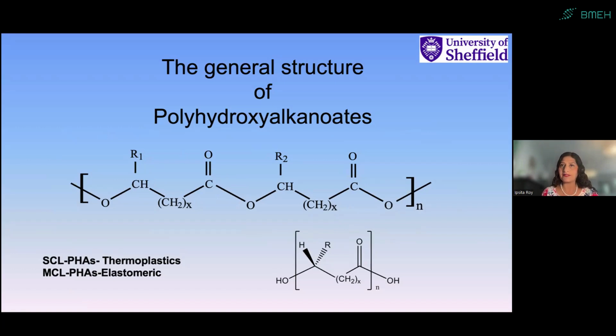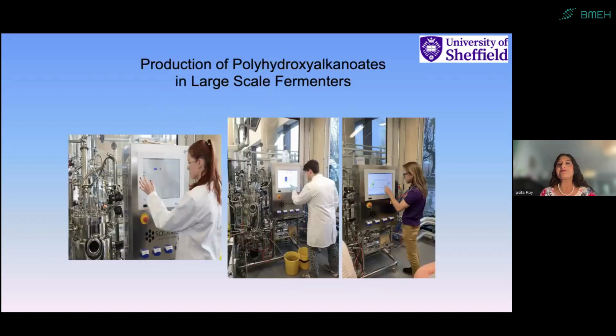The short chain length PHAs, as we call them, have monomer units going from C4 to C5, whereas the medium chain length PHAs are mainly monomer units going from C6 to C16. Normally the short chain ones are hard and brittle, although there is P4HB, which is FDA approved for medical applications, which is highly elastomeric. Medium chain length PHAs are always highly elastomeric in nature. We produce these polymers at large scale in Sheffield. We have a 30-liter fermenter as a pilot plant.